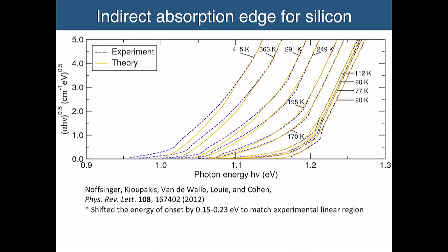And you see that. Let's go first to low temperature. Again, you see a straight line coming from phonon emission, another straight line here coming from phonon absorption. When you're at low temperature, of course, what dominates is the phonon emission, that's why it's much stronger, and phonon absorption is a weak contribution. And the difference in these two onsets is the phonon energy involved in the transition.